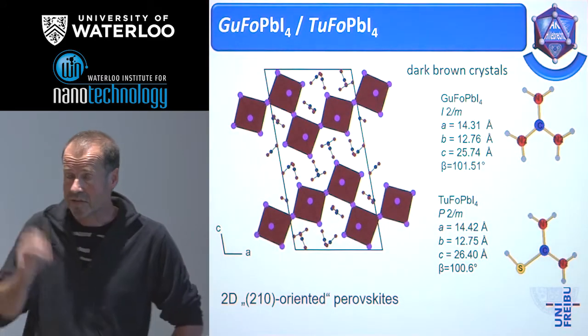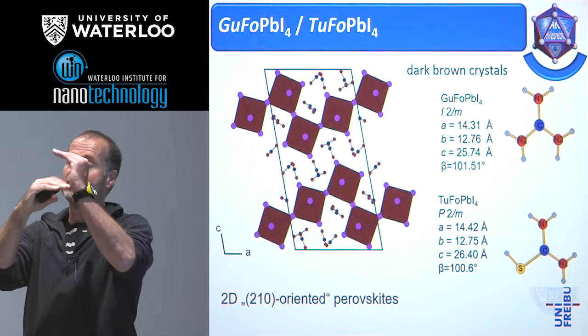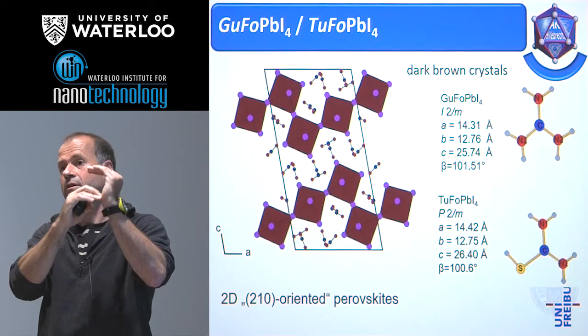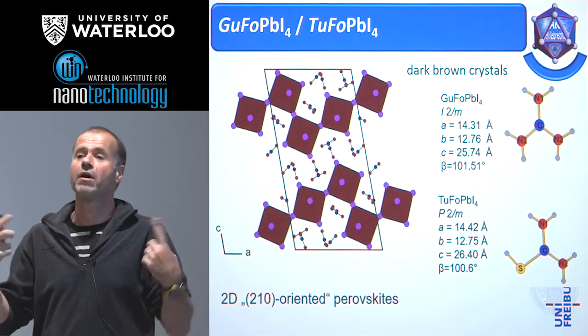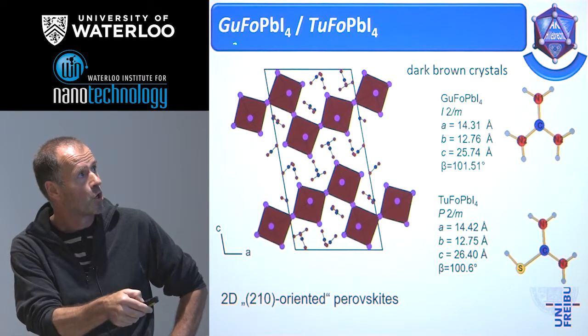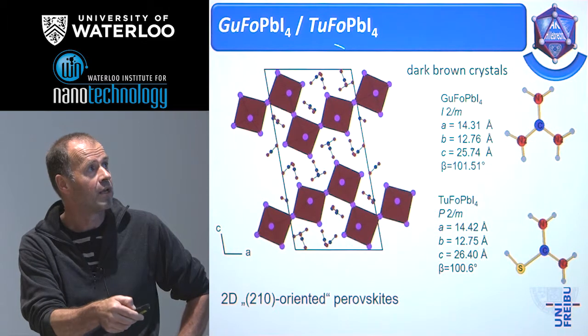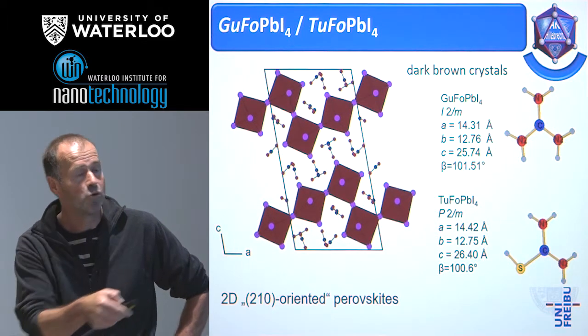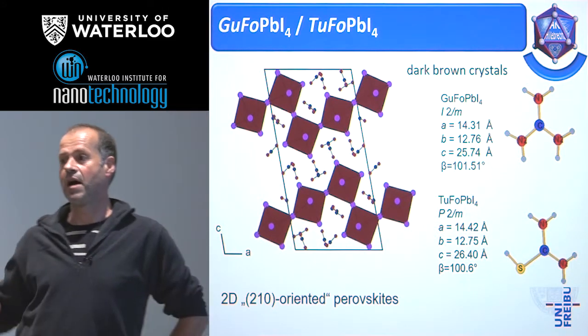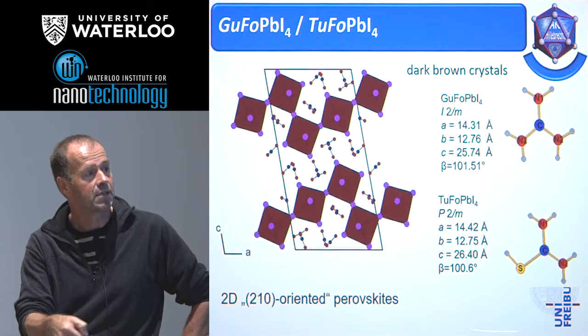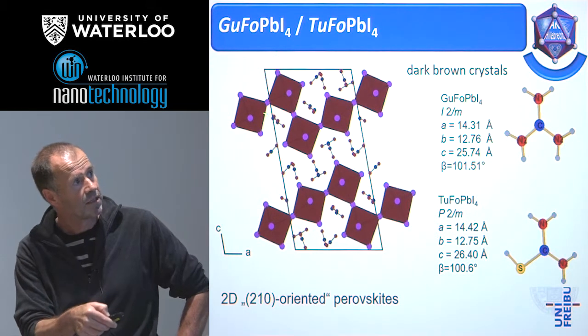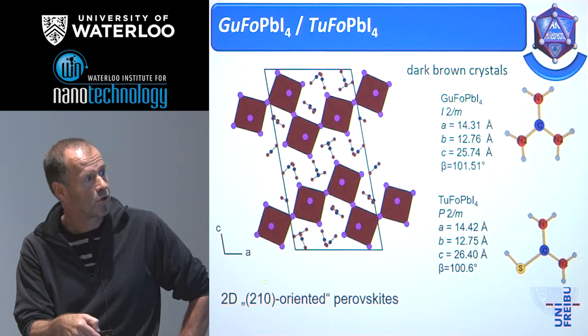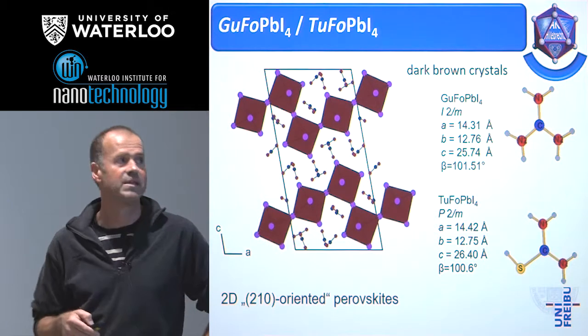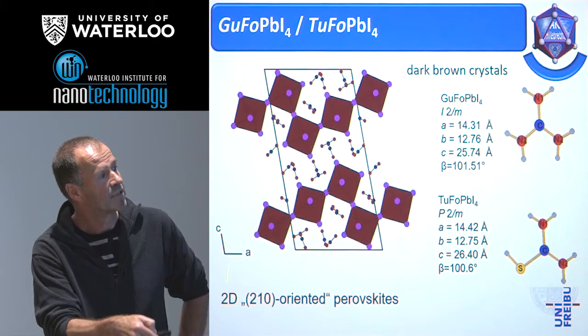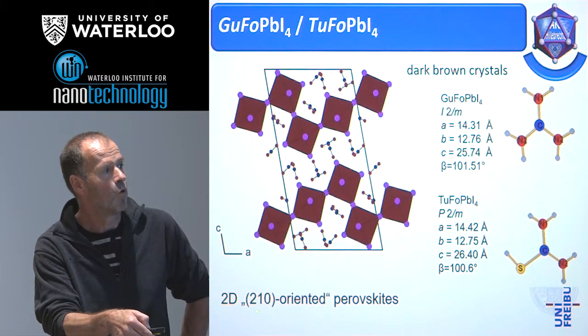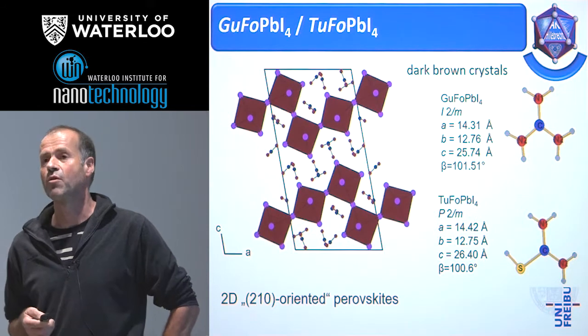The general idea, to have an influence on the dimensionality of the corner sharing octahedra in interaction with the organic cations, was shown by the combination of guanidinium with formamidinium, or with the abbreviation TU, that means thiourea cation. Now, that's a new cation we introduced to this perovskite structure, and we could show that we get samples which have a crystal structure of so-called 210 oriented perovskite. That means the cutout of the structure of the perovskite follows now the direction or the layer 210. And it was the first example, but it's also not useful.